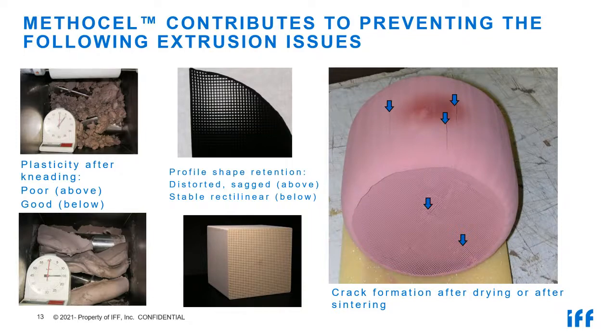A second typical problem is the so-called shape retention. Shape retention of your profile especially has a high importance when you extrude hollow profiles like honeycombs. Here in the upper picture, you can see a shape retention problem. In this case, it was extrusion of silicon carbide to a hollow profile, of course, in honeycomb. As you can see in the upper part of the picture, some segments collapsed a little bit. At least they are distorted and sagged, and this is off spec. You cannot sell it to a customer. Silicon carbide is expensive. This reduces your production speed and leads to off spec, which is costly. What you like to get is a stable rectilinear structure, as you can see in the picture below. And cellulose ether definitely contributes to the solution of such issues.